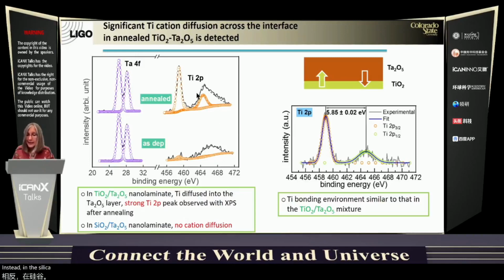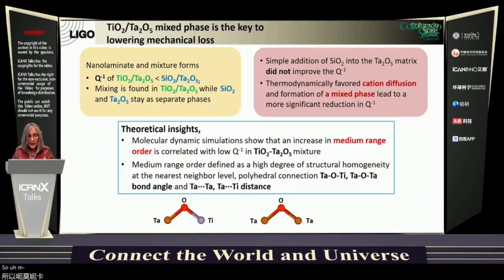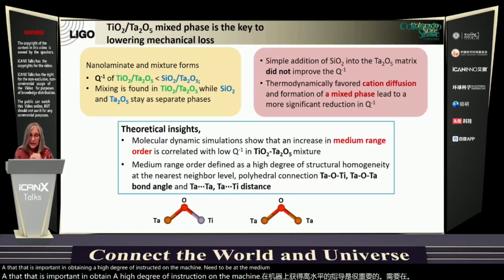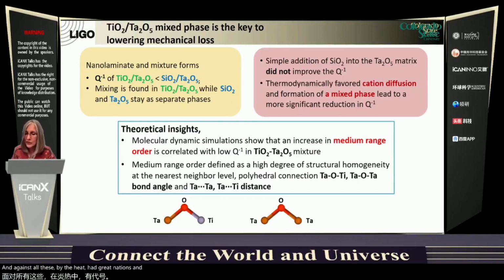And what I show here is that we have also observed this diffusion through X-ray photoelectron spectroscopy measurements that show that the titanium environment significantly changes. Instead, in the silica tantala nanolaminate, we see no cation diffusion. So models show that for titania doped tantala, it is the titania-oxygen-tantala bonding that is important in obtaining a high degree of structural homogeneity at the medium range, again through these polyhedral connections, and that reduces mechanical loss.